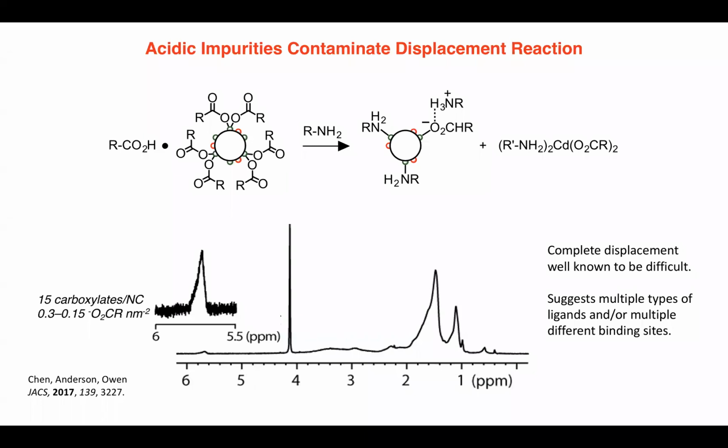And one of the explanations for this that we'll talk about is that when you add a neutral donor to a sample of cadmium selenide quantum dots with carboxylate ligands, for example, there are other reactions that can take place, like deprotonation of any associated carboxylic acid, and the formation then of this displaced cadmium oleate, amine-bound particles, and also these ion pairs.